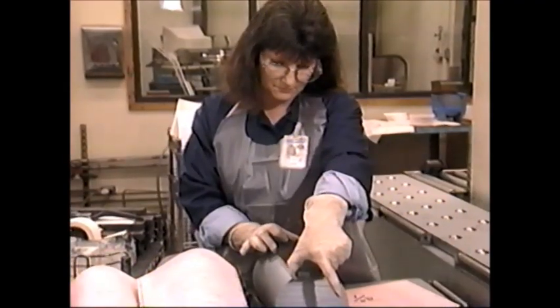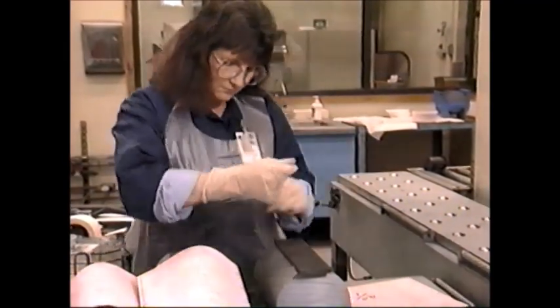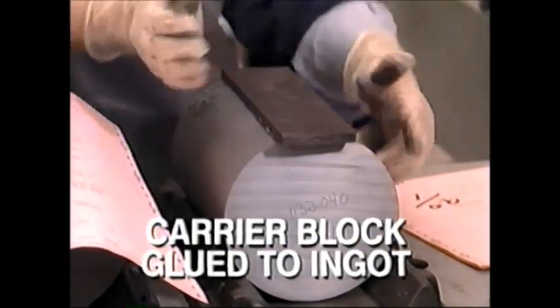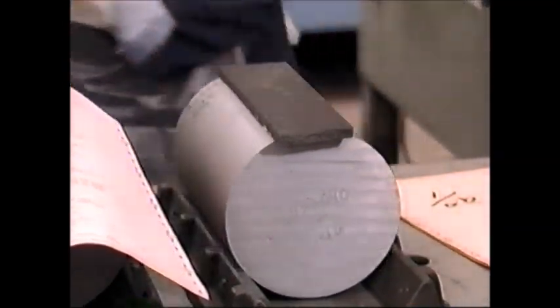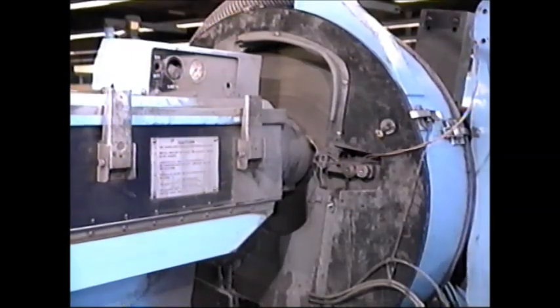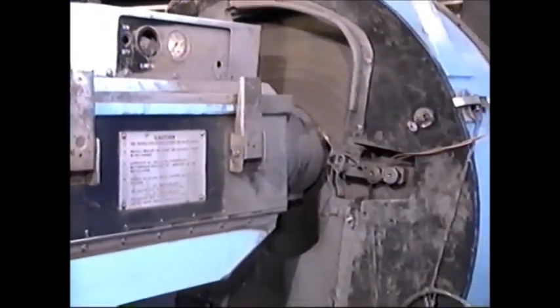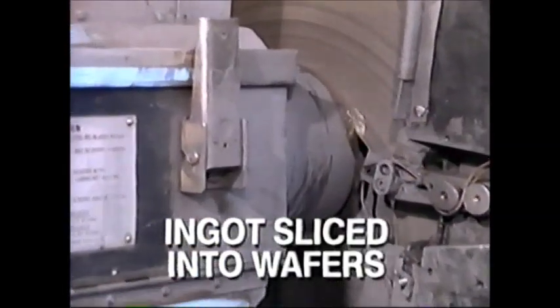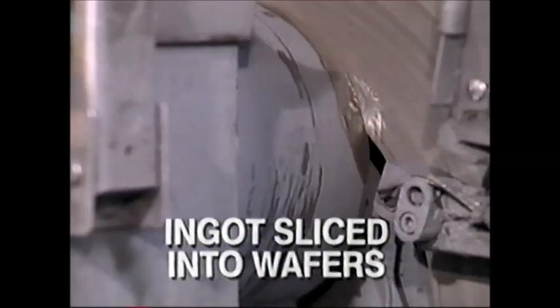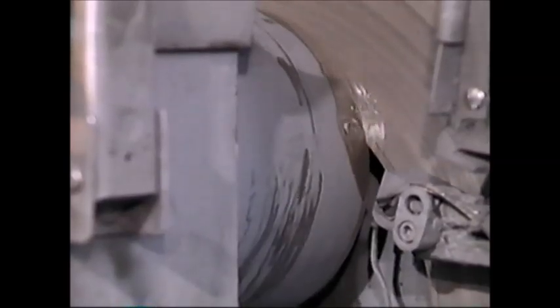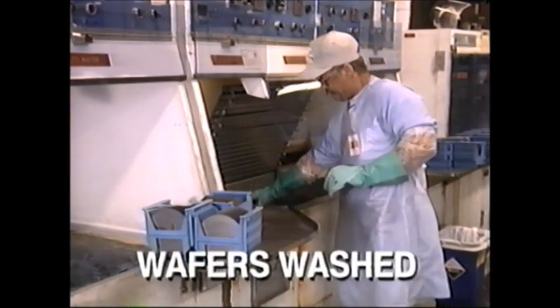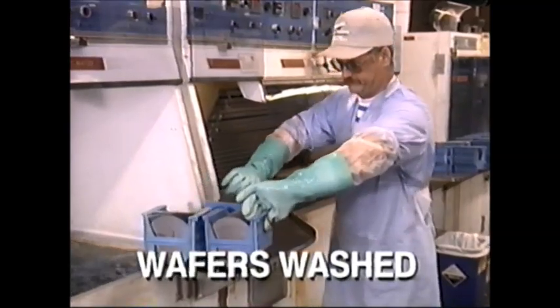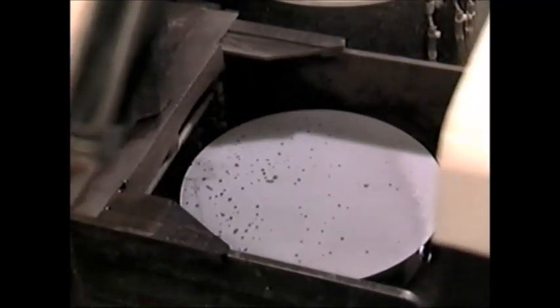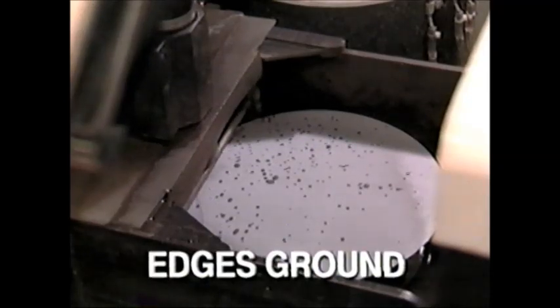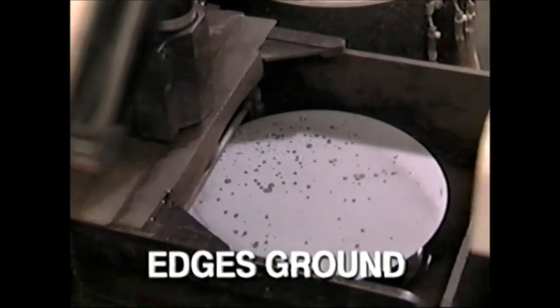To keep the thin wafers securely in place as they are sawed from the ingot, a carrier block is glued to the flat side. Then the ingot is placed in a very fine-edged diamond drum saw and sliced into wafers 20 to 30 thousandths of an inch thick using precise automation. The wafers are washed in a bath of deionized water to remove all particulate matter, then placed in a grinder to form a smooth profile on the razor-sharp silicon edges.